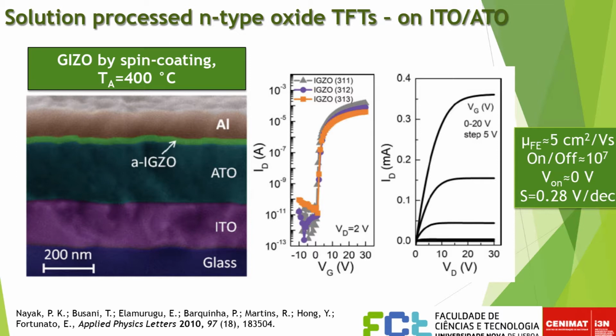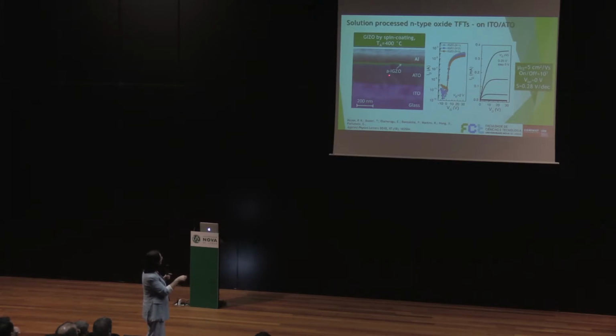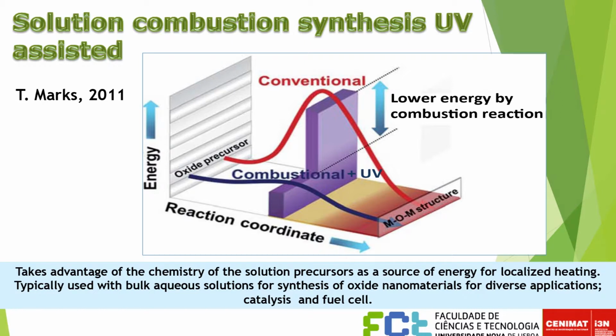Here we have a cross-section of the TFT showing all the layers. The green layer here is the IGZO, the semiconductor, and as you can see, the scale is 200 nanometers. Even though we are using low-cost materials, the amount of material that we are using is very, very small, just a few nanometers. More recently, since we want to decrease the final temperature, we use another approach that was followed by Tobin Marks at Northwestern University. Simultaneously with the heating process, we also use a UV process. So it's a combustion synthesis, and the idea is always to try to reduce the final temperature.